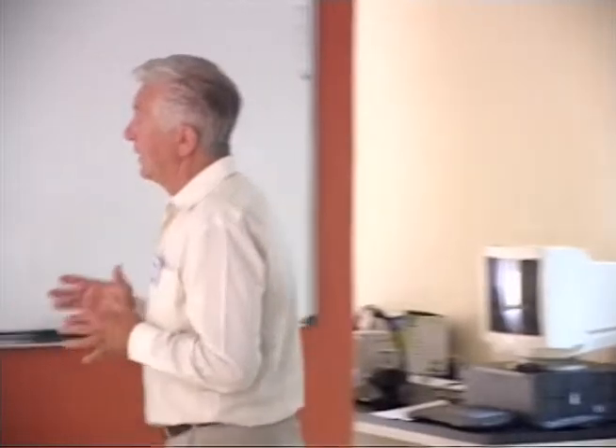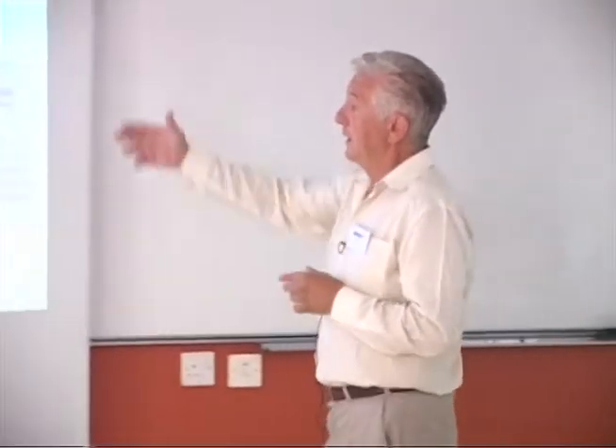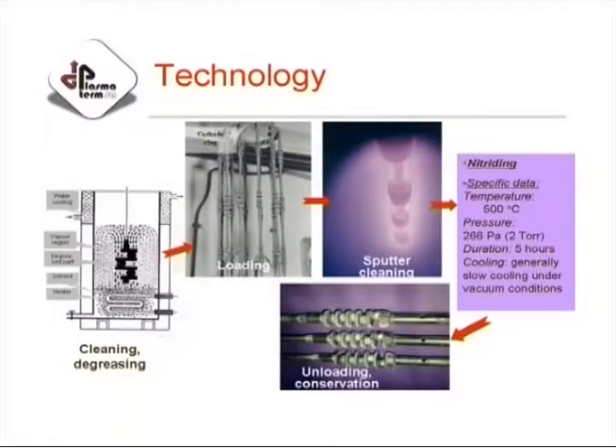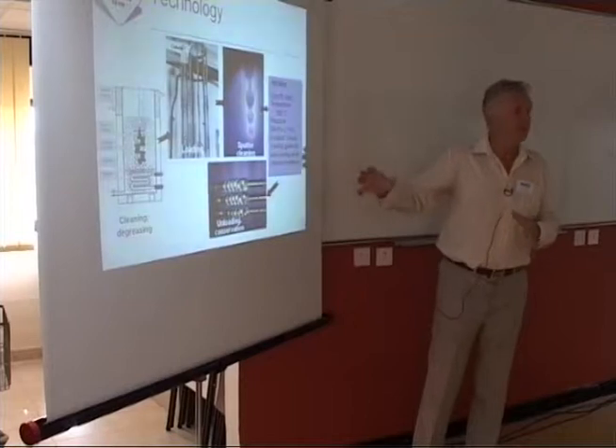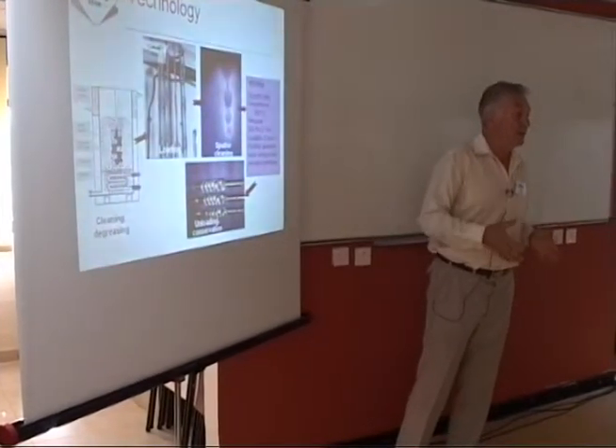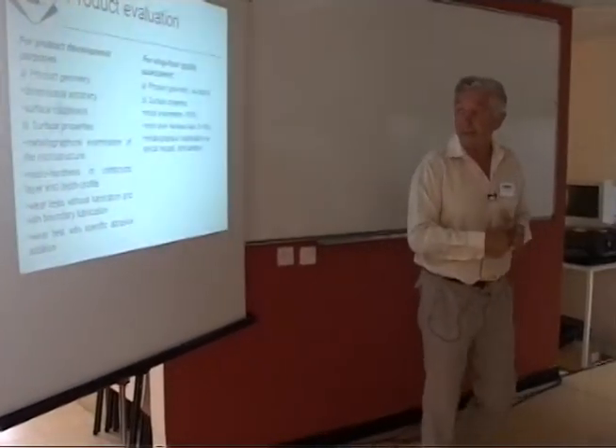And then certainly we come to the treatment, which is at a temperature of 500, 510 degrees centigrade, at a pressure of roughly 2 torr, duration 5 hours for these pieces, cooling generally slow cooling under vacuum conditions. That's what we apply here. And certainly then the parts are removed, tested, and packed.